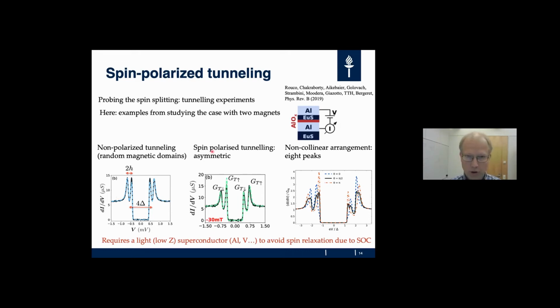Now, it's important actually that in this experiment, what was used was aluminum. It's a light element, and in a light element, the spin-orbit interaction is weak. In this case, you can see these peaks, you can resolve them sort of easily. If you would have heavier elements such as niobium, it would be much harder to see this splitting because of strong spin relaxation. I forgot to say that this europium sulfide here is the magnetic insulator.